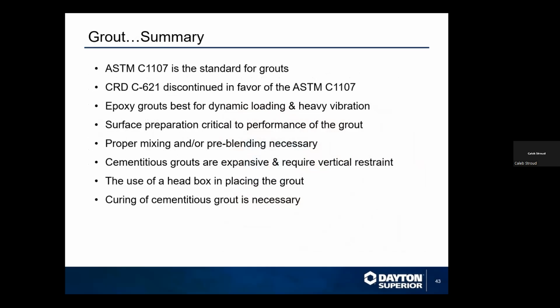And so to summarize this, as we wrap it up, we touched on the 1107 specification and why it's important around the non-shrink grout. We referenced the Corps of Engineers in favor of 1107. Epoxy grouts are best for dynamic loading and heavy vibration. We also covered surface preparation, proper mixing, cementitious grouts and required vertical restraint, and the use of a head box and in-place grouting and curing as well. So that should summarize it.